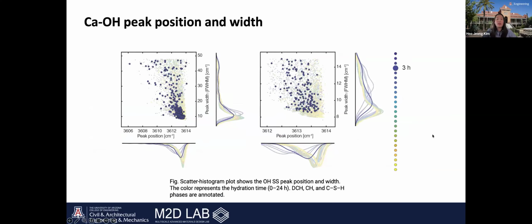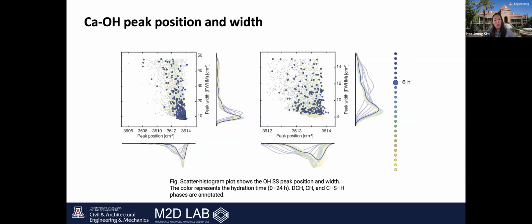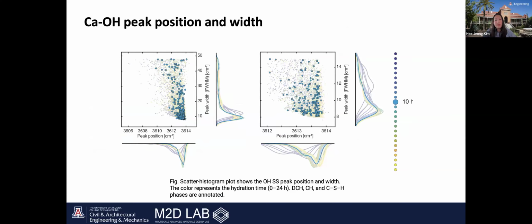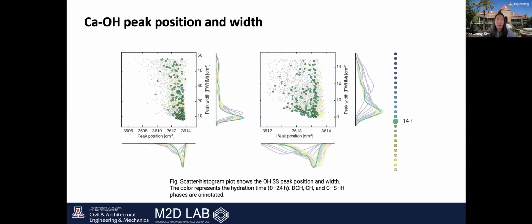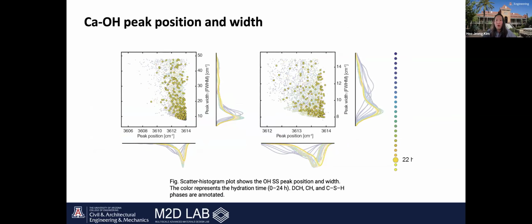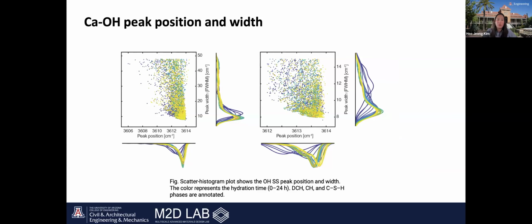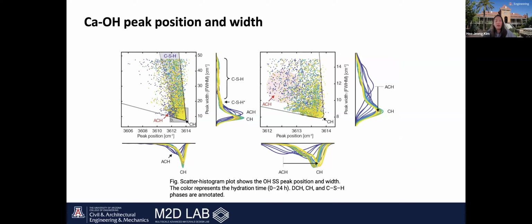This slide shows an animated plot of the CaOH peak position and width. By tracking these values over time, we can clearly see how the CaOH peak changes during the early hydration process. From this analysis, we discovered a new phase, which is an amorphous or disordered form of calcium hydroxide, which we call disordered calcium hydroxide, DCH. We found that this disordered CH acts as a precursor to crystalline calcium hydroxide, forming before the setting process begins. This discovery gives us new insight into the early hydration mechanism and helps explain the formation pathway of calcium hydroxide in cement.